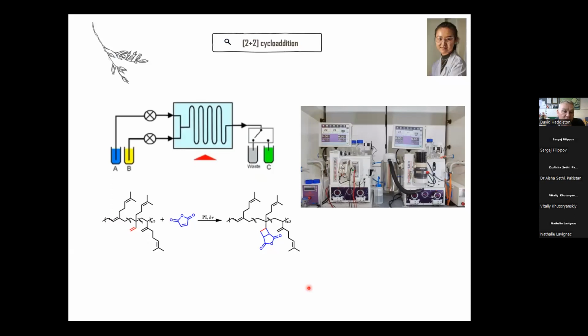And then we do that in flow. So what we're doing here is anionic polymerization in flow. We then modify it electrochemically or we modify it photochemically. And the photochemical modification we do, bearing in mind we can change the chain end to be a ring open epoxide, so we've got a different chain end. We've now got control over this 1,2. Here we're doing a maleic anhydride 2+2 photo addition to introduce some maleic anhydride, which we then ring open with an amine. That's quite conventional for this type of chemistry.